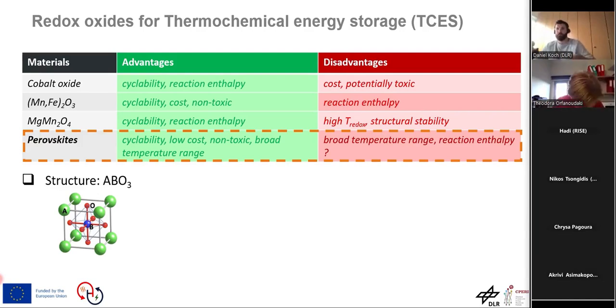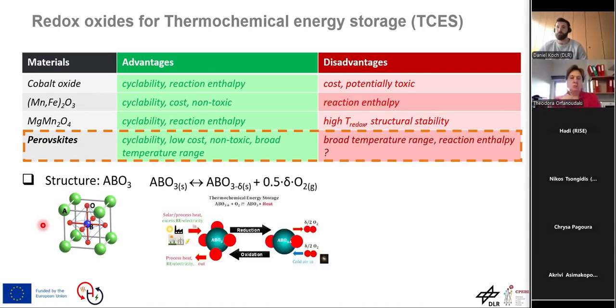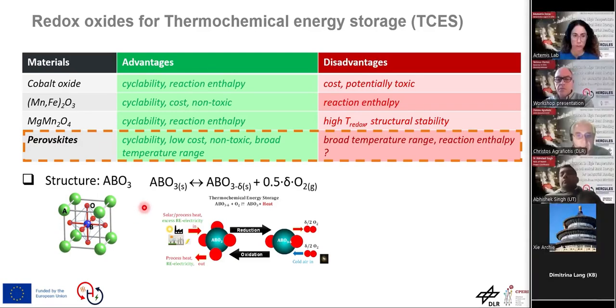For those who are not familiar, perovskites are mixed oxides of the formula ABO3, so it involves two cations and oxygen. And if we click, we will see how this will operate. The thing is that they operate as a partial reduction scheme. As you can see here, when they are heated, for instance, they don't go all the way to the reduced state of the oxide, but they lose a lesser amount of oxygen, which is denoted by the Greek delta and means the reduction extent. So they don't suffer any phase transformation. Essentially, they transform to an oxygen-lean solid oxide.